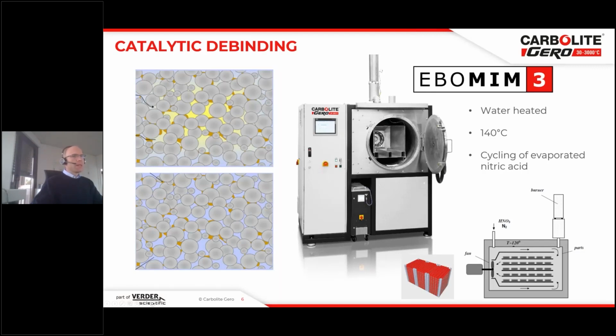So what does it mean? We purge into that furnace nitric acid, HNO3. We evaporate the nitric acid. So we have a mixture of nitrogen and nitric acid, which is cycled over the parts by means of this fan. And this is the way how you catalytically get rid of the main binder.